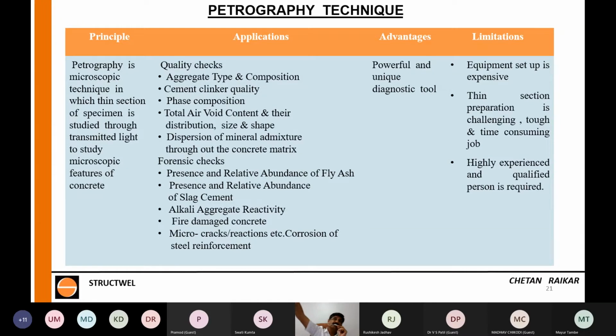I have actually done this experiment, on, I think, if I'm not mistaken, a footing about 3-4 meters by 20 meters long, and the client wanted to know whether the fly ash had dispersed properly. So we took 30-40 small samples from various locations in the same footing, prepared petrographic thin sections out of them, and certified that yes, because you can actually see a fly ash particle under the microscope in a thin section. So we could very confidently tell the customer, there was no other way of finding whether the fly ash dispersion within the body of concrete was uniform, and that was a very key property for some usage of theirs that was important.